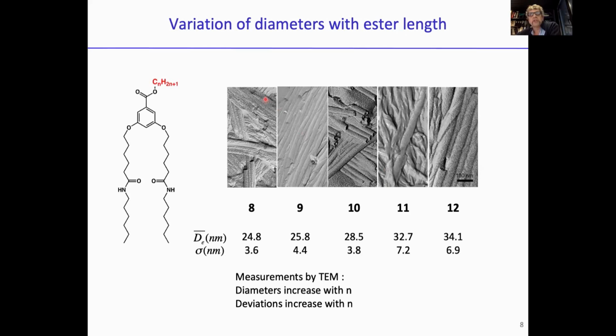So this is the regime of what happens between 8 and 12 carbon. And you can see all these nice pictures that we got from freeze fracture TEM. And you can see from 8, 9, 10 and 11 carbons, we have quite nice nanotubes. 12 is quite an exception because we have a mixture. We have some nanotubes and other, I would say, other kind of objects.